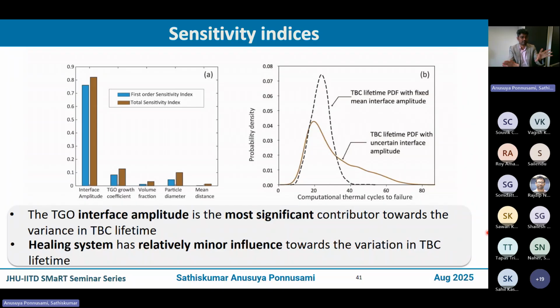Of course, you can look into the Sobol indices for the first order and the total sensitivity index of all the 5 parameters, which also reflects what I just told in the previous slide. The interface amplitude and the TGO growth coefficient are the primary contributors for the lifetime, which means the other 3 parameters, which are to do with the healing particles, are not that important for the self-healing system to be optimal. That is useful because material scientists do not have to worry about whether the particle diameter should be exactly 20 microns, or is it okay if we have 16 microns or 24 microns. The answer is, it doesn't matter. So that's the level of confidence that you can get.